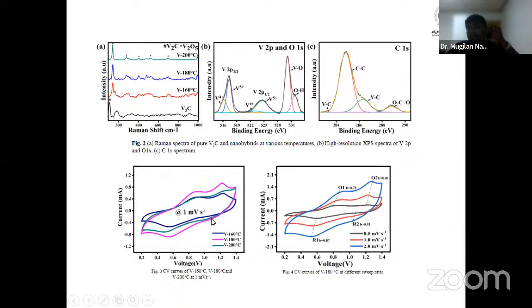I have done the CV curves for V160, 180, and 200. I noticed that the slope and plateau for V180 are much better when compared to V160 and V200. In V160, the V2O5 is still not present, so it depletes the V2C structure, whereas in V200 the V2O5 suppresses the V2C performance. So finally, I noticed that V180 gives the better performance, also using the CV curve. A pair of oxidation and reduction peaks was found, which is highly pertinent for zinc ion battery performance, and for reversible and irreversible capacitance retention.